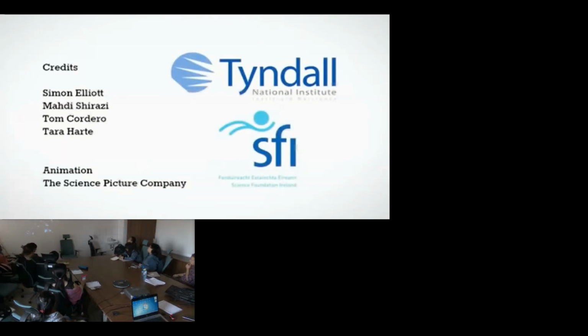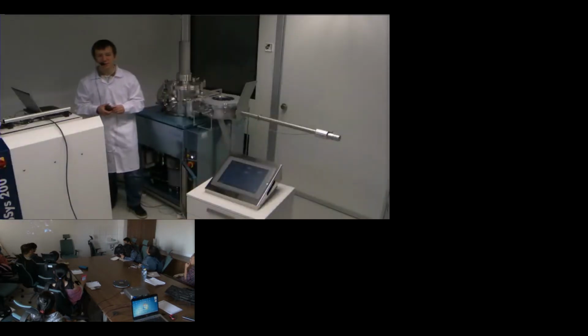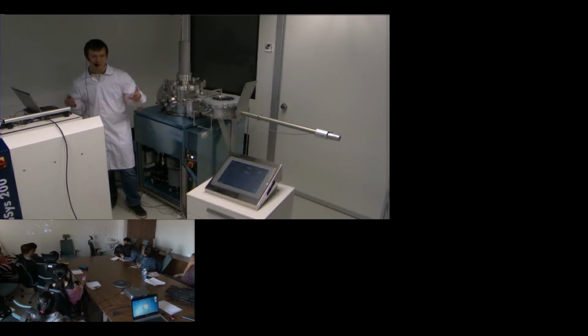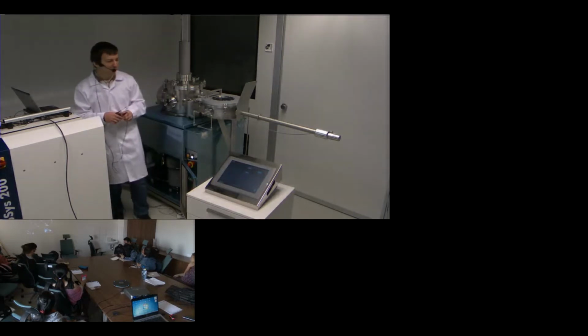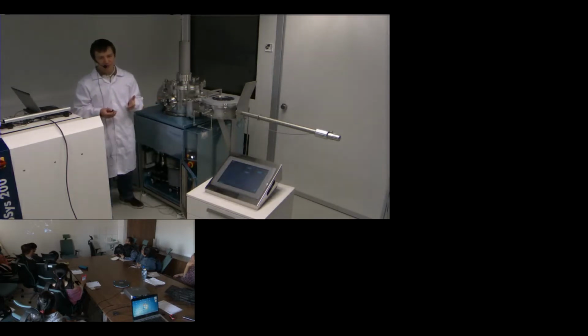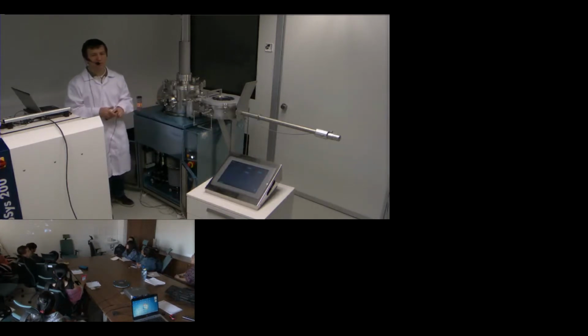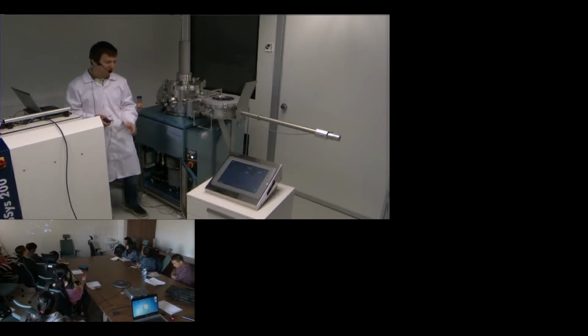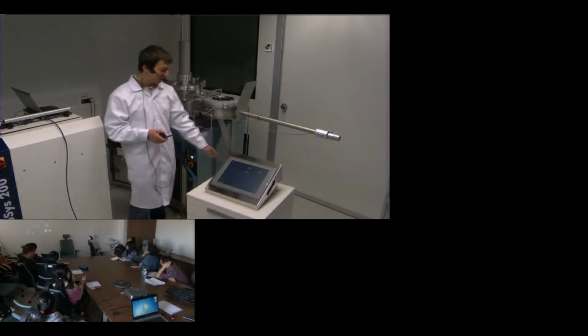So what is important for this technique is that the deposition is from the gas phase. So even if you have porous materials, like for example, we had a bone implant here, which some medicines gave us, and this implant had the structure of a foam, so it has a lot of pores, so it was a very porous structure. So we are able to cover this implant with a biocompatible layer everywhere, not only on the very outer surface, but also inside the pores, so it's fully covered.